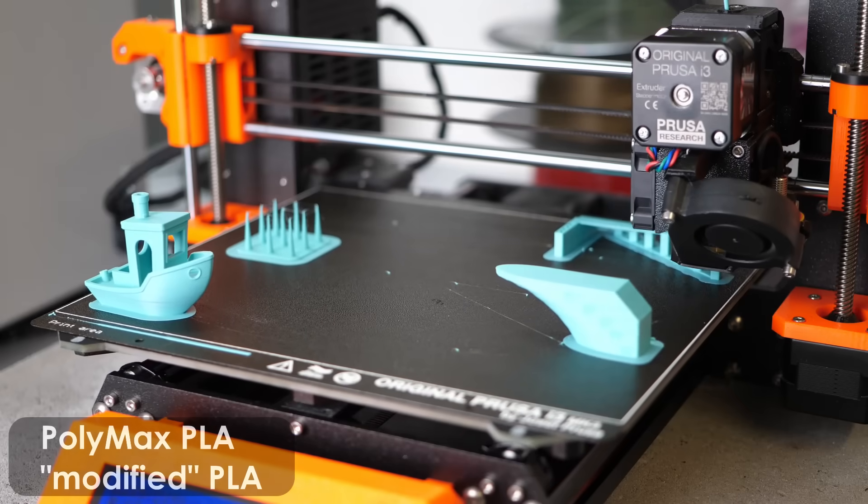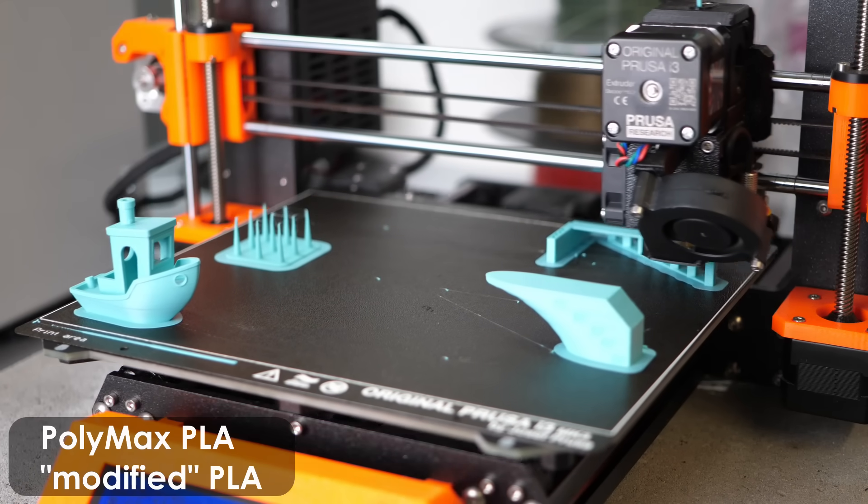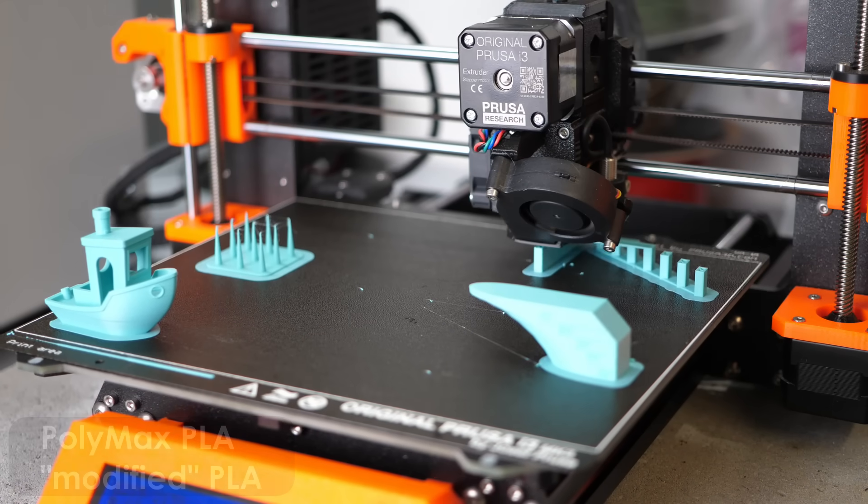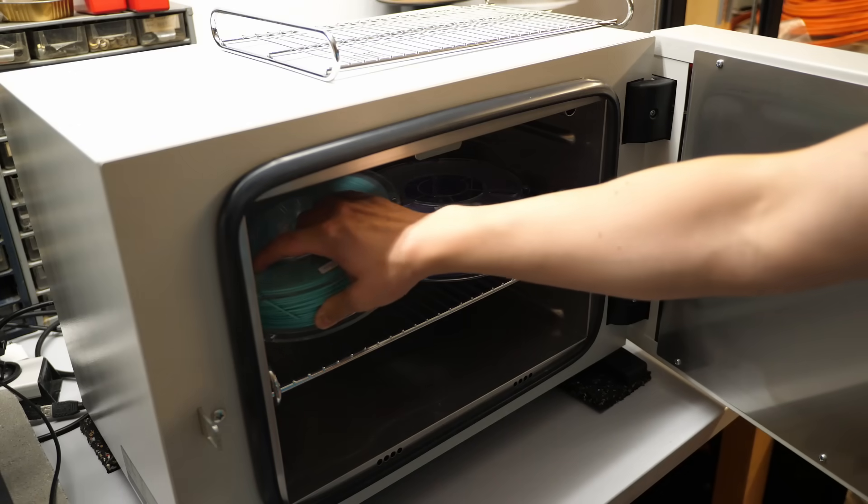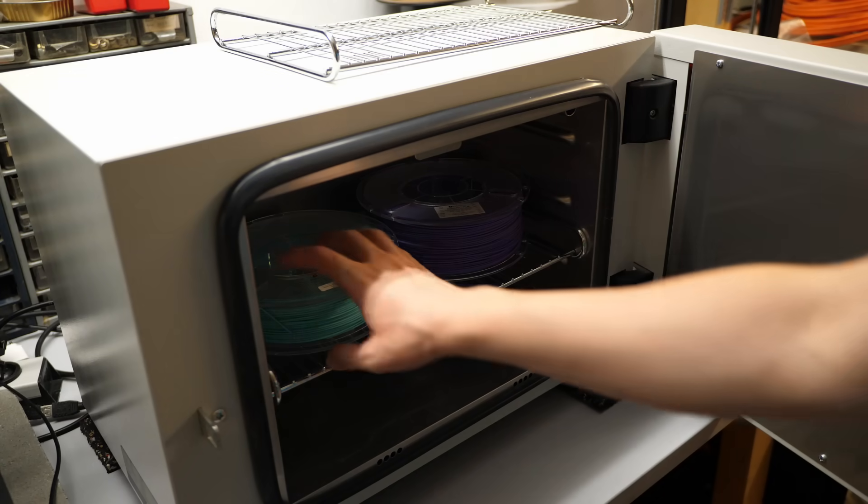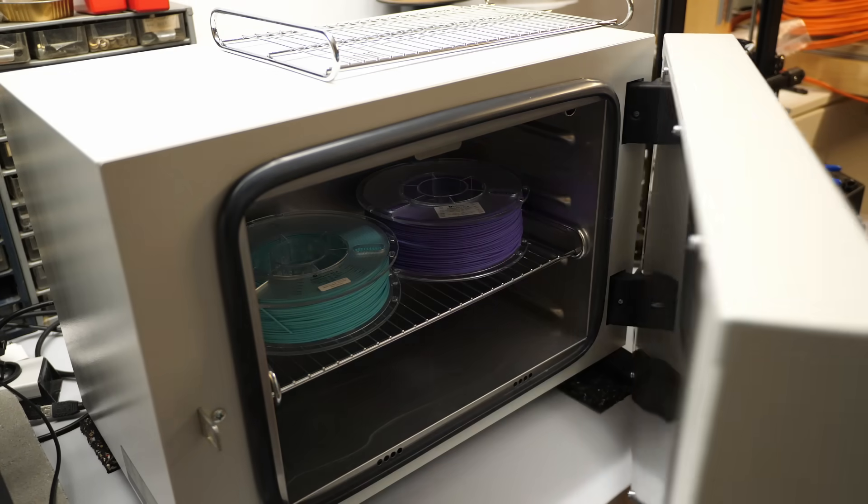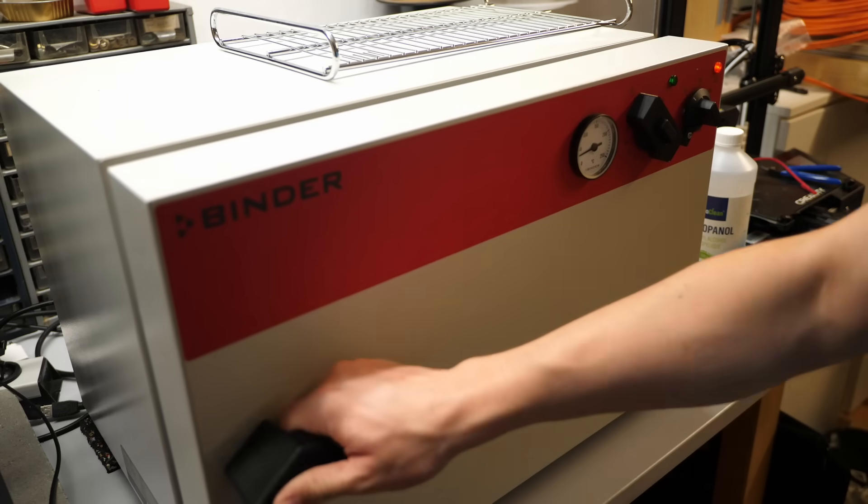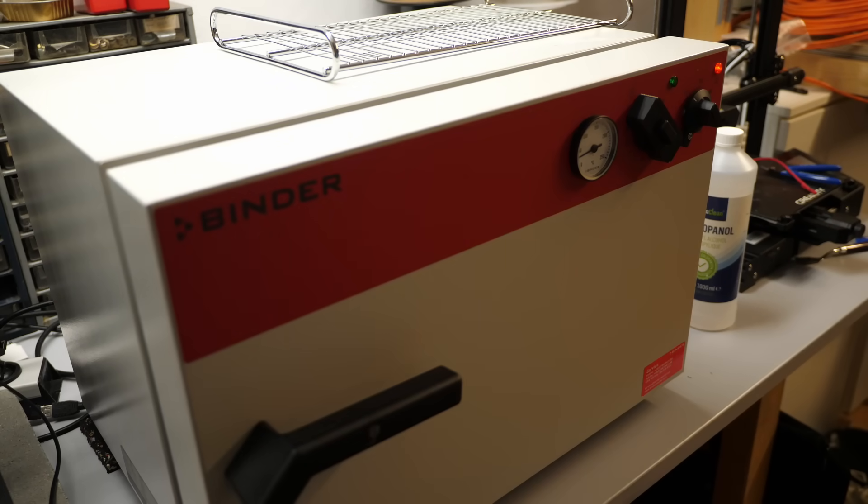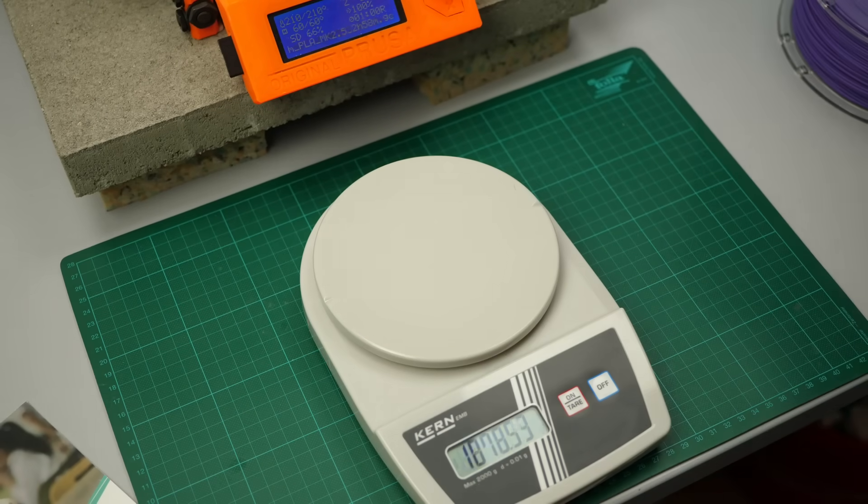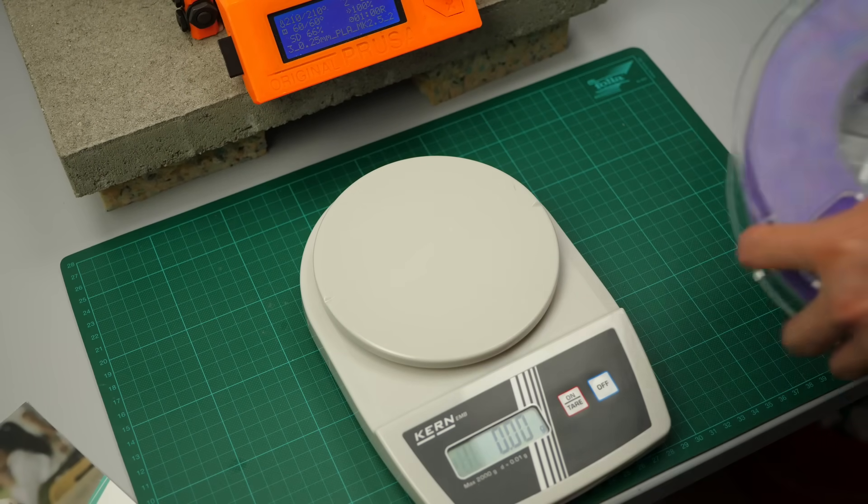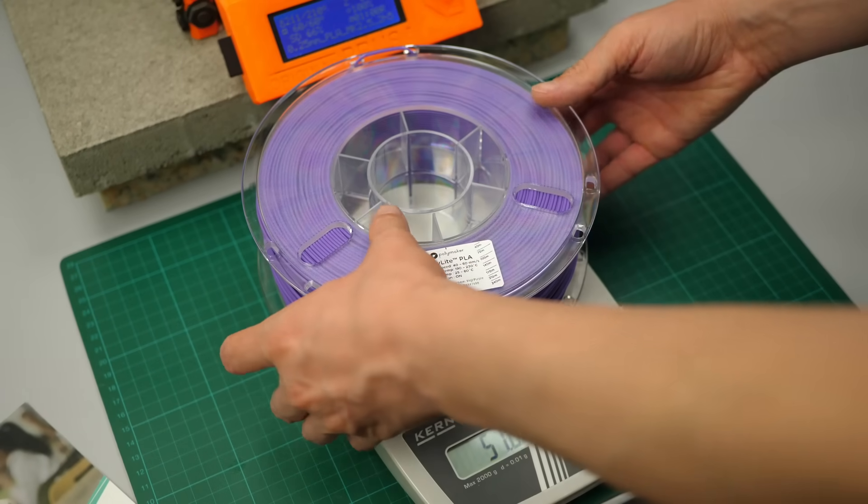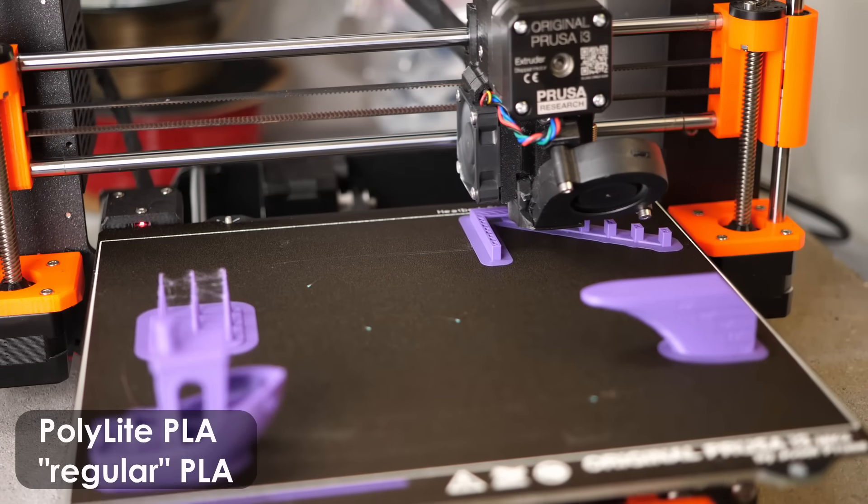First I printed a bunch of quality test parts to see if the print results differ. I dried both spools after I took them out of the box to not run into trouble with moisture in the material. I removed 0.16% and 0.23% of moisture which is not a lot and I don't think that any of the spools took up a considerable amount of water while being packed. Both printed without a problem.